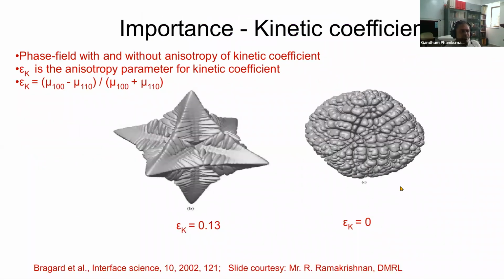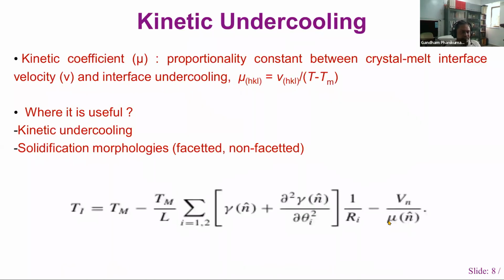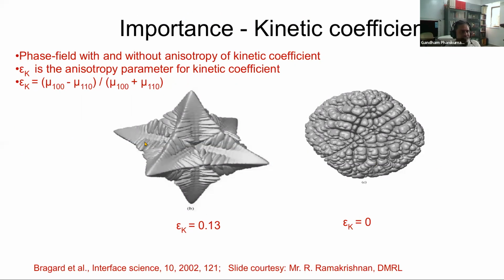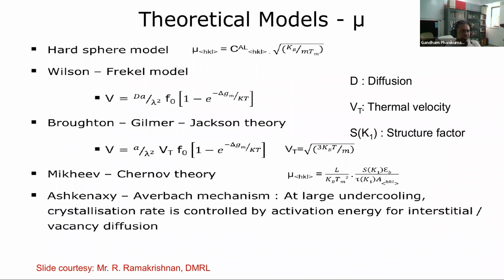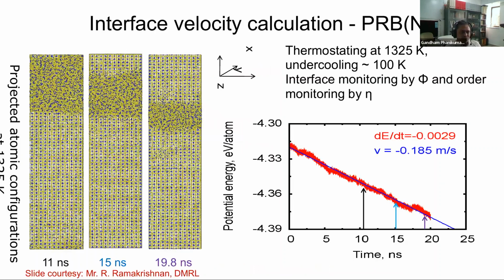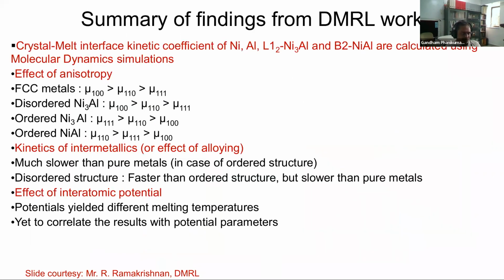Now, all those things will lead to morphology changes. The kinetic coefficient itself, this mu, is different in different materials. It can be anisotropic, so that a growing crystal can be a beautiful dendrite like this, or it can be like a ball, which is isotropic. So anisotropic growth or isotropic growth are both possible for a given material, depending on the anisotropy of the kinetic attachment coefficient. Now, there are models available for this. We have done that work, and we can simulate the growth of the solids in a molecular dynamics framework and determine some of these coefficients. That was done by Ramakrishnan during his PhD, and we have found which plane and which direction have less energy, for example interface energy, and what is the magnitude of difference with respect to the faster and slower phases, for example.